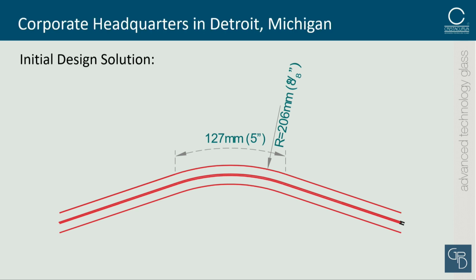They had this idea of the diamonds, and this was the shape of the glass to begin with. It had a radius of 200 millimeters and 2 flat parts. And 200 millimeters is a very tight radius for a coating. If we go by the book, coatings won't take less than 1,500 millimeters. This is almost 8 times less than that.